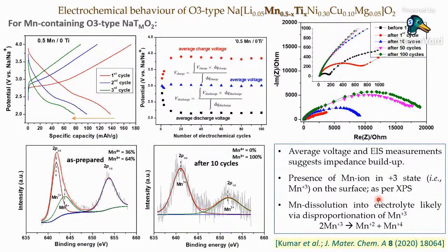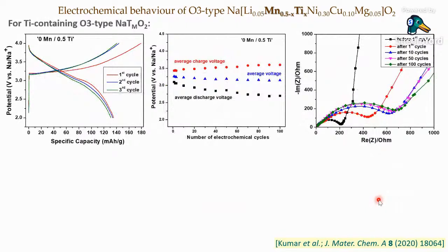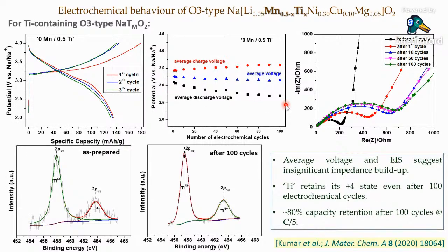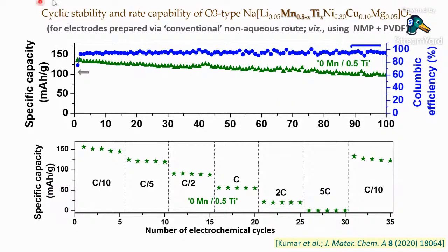Getting an electrochemically and structurally stable layered transition metal oxide is actually very, very difficult, and that was again shown by our material. Now, when we had titanium and no manganese, as in this case, we could see almost no increase in the polarization up to 100 cycles, and all the ions were stable in the oxidation state they were supposed to be. And in terms of cyclic stability, it showed very good cyclic stability compared to the 0.5 manganese, 0 titanium containing counterpart.